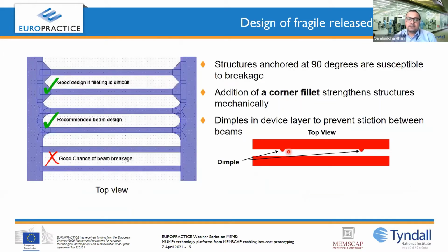Now there is some more design that a designer must follow while designing fragile release structures. If a designer wants to design a few beams, and the beams are anchored at 90 degrees, they are very prone to breakage because of the inherent stress mostly in this junction. Therefore, a corner filleting is always preferred. If it is an arc, that is the best one. If not, at least a straight line would be good. Without any corner filleting, this is not at all recommended.